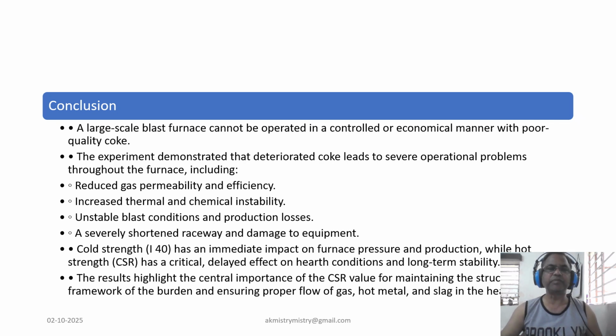In conclusion, this experiment provided definitive proof that a large scale blast furnace simply cannot be operated in a controlled or economical manner with a poor quality coke. The use of deteriorated coke causes severe system wide problems from the top of the furnace to the hearth. Cold strength I40 immediately impacts gas flow and production, while hot strength is fundamental to the long-term structural integrity of the hearth, which is crucial for the flow of gas and liquid product. The central importance of CSR value cannot be overstated. This study makes it clear that investing in high quality coke is not a luxury but a requirement of reliable, efficient, and safe blast furnace operation.